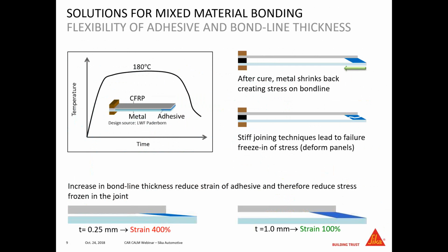When we consider a part that is bonded together on one end, consisting of a metal piece and a CFRP piece, for instance, when this is cured in the E-coat oven, the metal is already expanded, and after the oven, the metal tends or will shrink back to its original dimensions, and actually creating stress on the bond line. And if you have a very, very stiff material, then this leads to failure or freeze in of stress and then deformed panels. So one solution, or the solution in terms of joining, will be to use a more flexible system, and that's what we propose with the MBX materials.